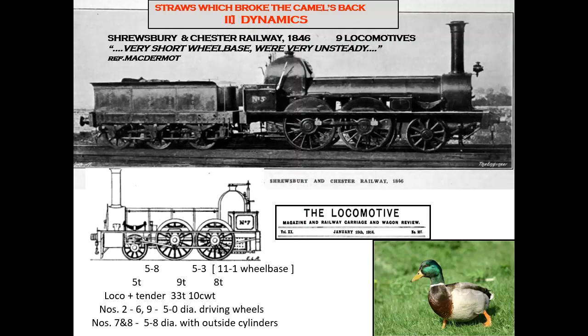The other straw which broke the camel's back, I believe, is dynamic effects from the locomotive. Now at the top you'll see a photograph of one of the locomotives of the Shrewsbury and Chester Railway, which had only been formed in 1846. They only had 9 locomotives, and 8 of them looked like that one. Now, there's a note in McDermott, Great Western Railway, because this railway was later taken over by the Great Western Railway. These locomotives had a very short wheelbase and were very unsteady. You can see that the wheelbase is actually less than half the length of the locomotive.